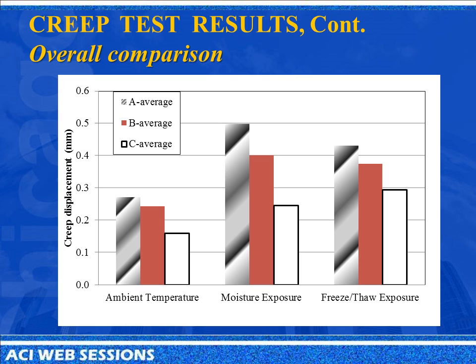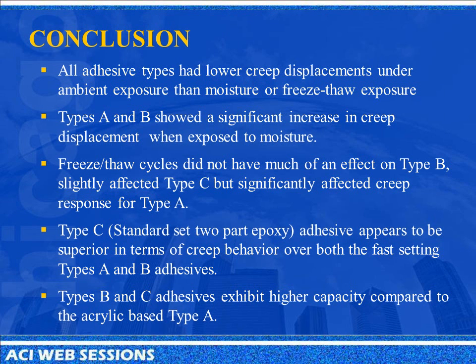So the first one would be ambient temperature. The one on the left is type A, then type B, then type C. And you can see the effects of the moisture when you compare the three specimens. To conclude, all adhesive types had lower creep displacement under ambient temperature compared to moisture exposure and freeze-thaw exposure.